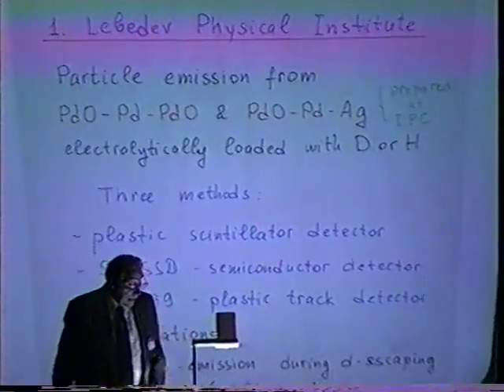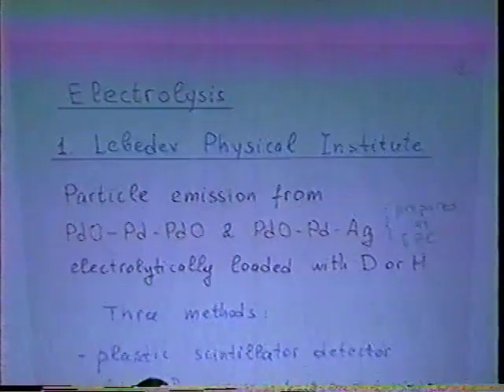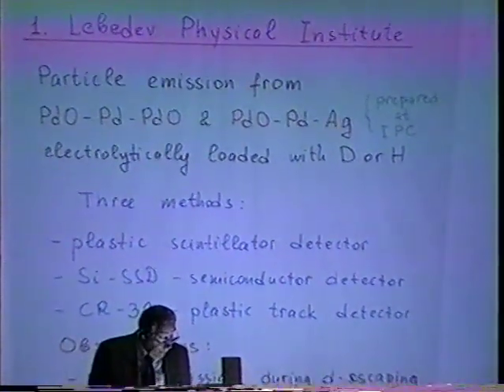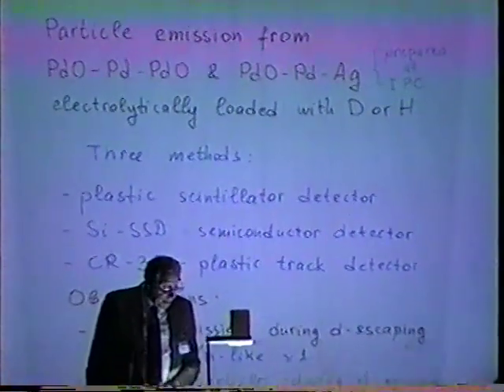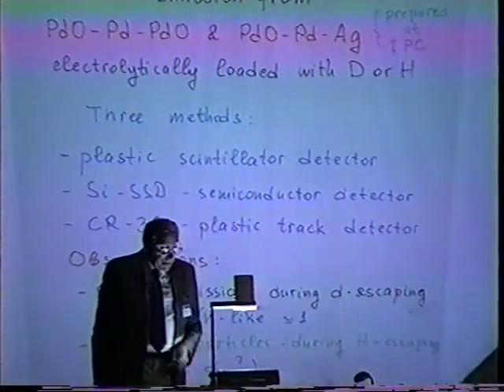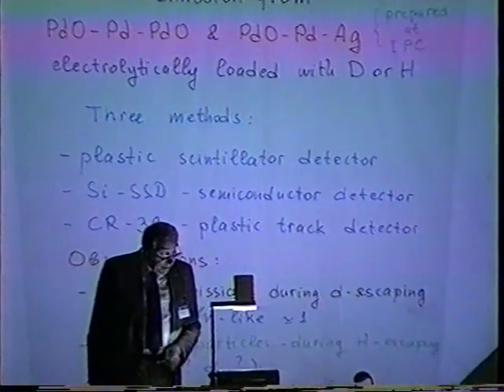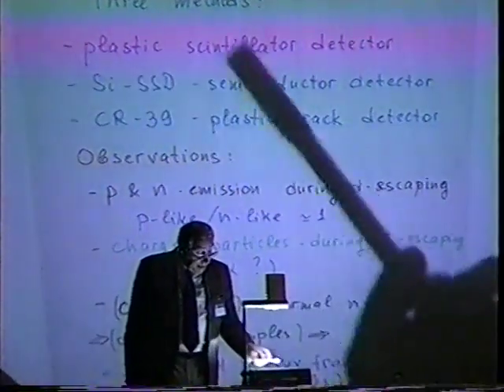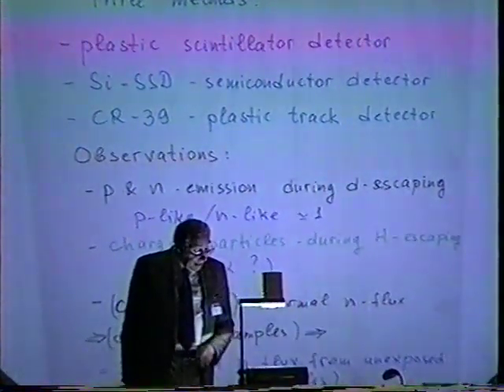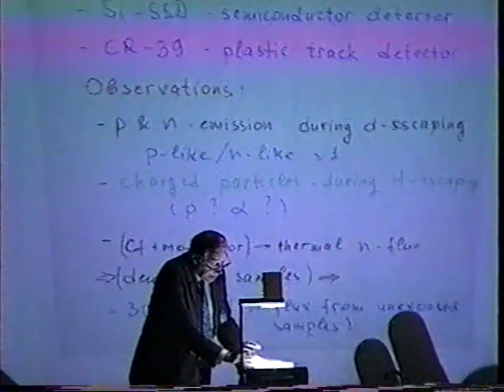Now, about our cold fusion work. I'd like to start from classical electrolysis, and I want to present a paper from the Lebedev Physical Institute group. This group measured particle emission from sandwich samples with this and this composition. These samples were prepared at the Institute of Physical Chemistry and electrolytically loaded with deuterium and hydrogen. For measurement of products, three methods were used: a plastic scintillator detector, a semiconductor detector, and a CR-39 plastic track detector.